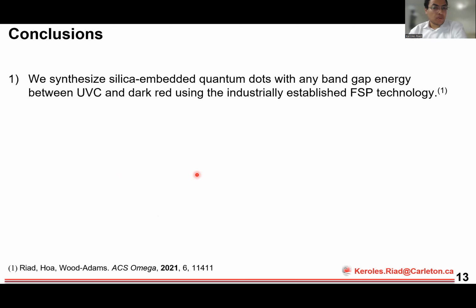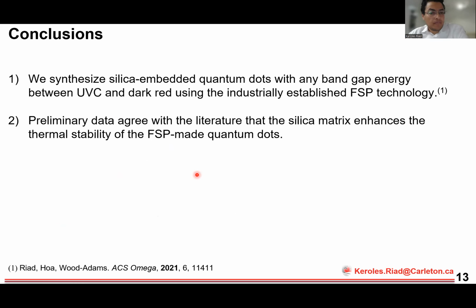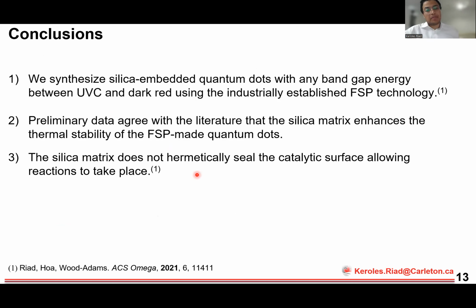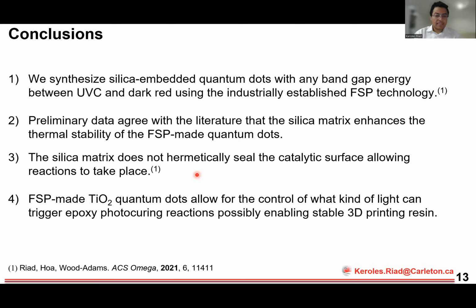So in conclusion, we're able to synthesize silica embedded quantum dots with any band gap energy between the UVC and dark red using the scalable FSP technology. And preliminary data agree with the literature that the silica matrix enhances the thermal stability of the FSP made quantum dots, and that the silica matrix does not hermetically seal the catalytic surface, allowing the reaction to take place. And FSP made quantum dots do allow control of what kind of light actually triggers catalytic reactions. I used the example of epoxy photocuring with the goal of enabling stable 3D printing resin.